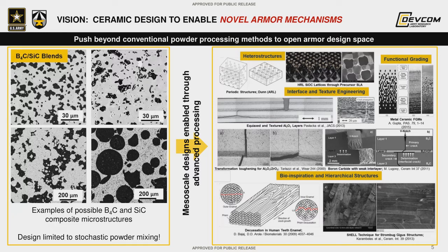Our overall vision here is to leverage ceramic design to enable novel armor mechanisms, not so much by creating new materials or just controlling the processing, but allowing us to push beyond conventional powder processing methods to open up the armor design space. So conventionally, when you mix two ceramic powders together, you're limited to doing things like stochastic powder mixing, which is where you take boron carbide and silicon carbide powders, mix them together at various different length scales of mixedness, and then hot press or pressurelessly sinter them into an armor plate.